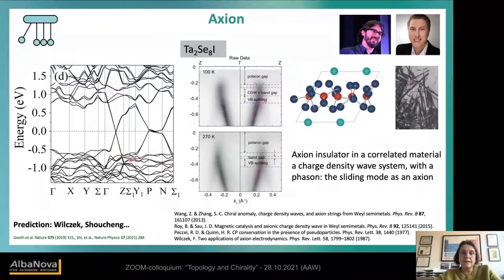And then we measured the transport, and we were disappointed because the material is insulating, and a Weyl semimetal should be semi-metallic. We expected a property like in tantalum phosphide and so on. And looking into the ARPES data, it shows you have this linear dispersion in this compound, but you have a small gap around the Fermi energy. And then we looked in the literature, and this is because we have a charge density wave.